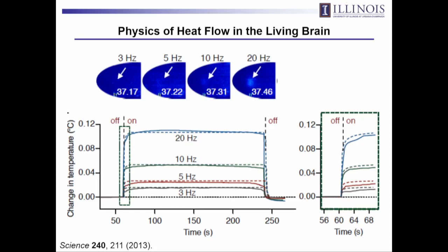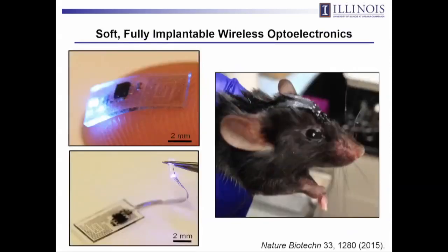And this is what's showing then. This is change in temperature measured in situ using that temperature gauge, very similar to the ones that I described for use on the skin, so super high precision. And we can measure the steady state increase in temperature at different repetition rates with fixed pulse duration. So we're changing the total thermal load. And even at 20 hertz, we end up with peak temperature increases that are only about 1/10 of a degree, so 10 times lower than the damage threshold, and in quantitative agreement with thermal models of the heat flow. So this is good, and we sort of lucked out for those 3 reasons that I just mentioned to you. So you can get LEDs in the brain without a problem.